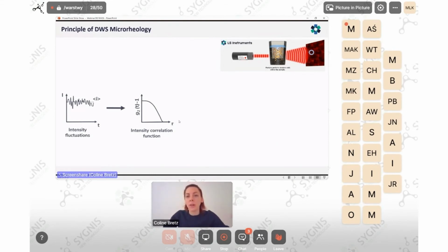We're looking at a bulk analysis at multiple scattering. So in this case, we don't get an average particle size, but we can get the mean squared displacement of the particle, which is an averaged value, of course. This tells us how free the particles are to diffuse in the sample. And typically for a purely viscous sample in which there is no elasticity, we will see a linear behavior. So the particles diffuse with time unrestricted.